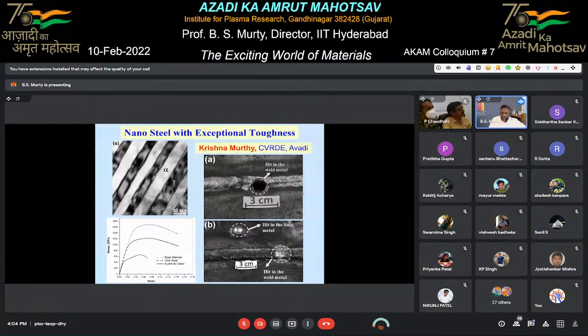Whereas if you take the same steel and do what is called thermomechanical processing, you can convert the microstructure into an extremely fine microstructure. This is what is called nanostructure. We can make that nanostructure and we call it nano steel, and it gives you such a high stress strain diagram where the toughness is very high. The area under the curve in a stress strain diagram indicates toughness. And once you make such an alloy, now you weld it. You see the welded joint is so tough that you fire a bullet, nothing happens. The base metal also is so tough that you fire a bullet, nothing happens.